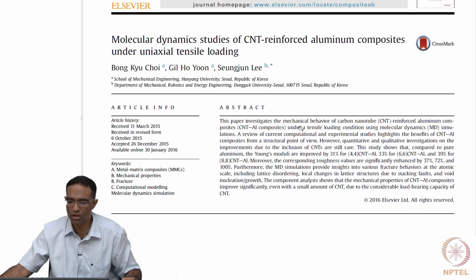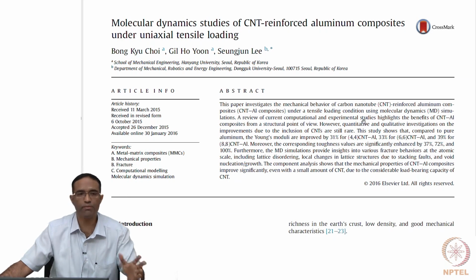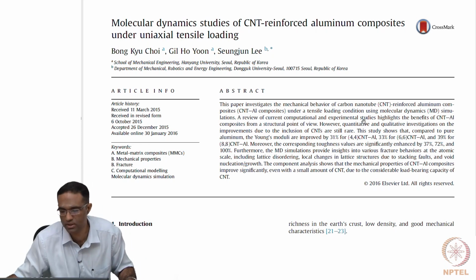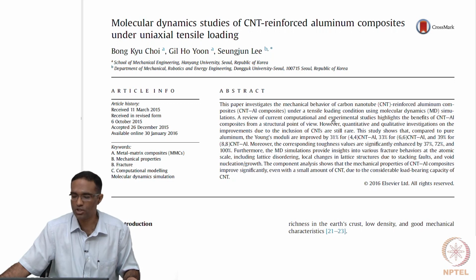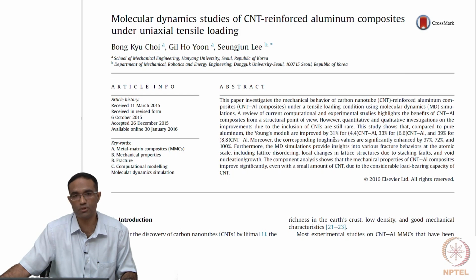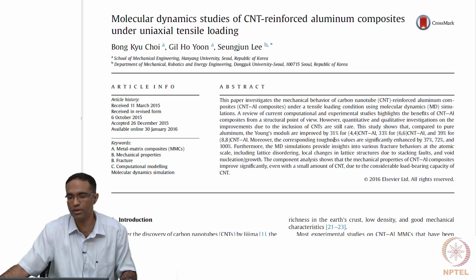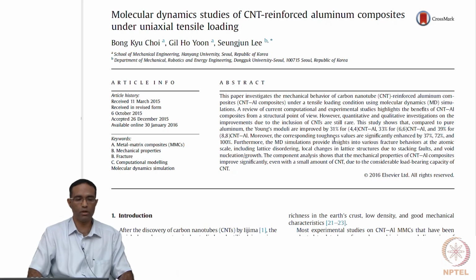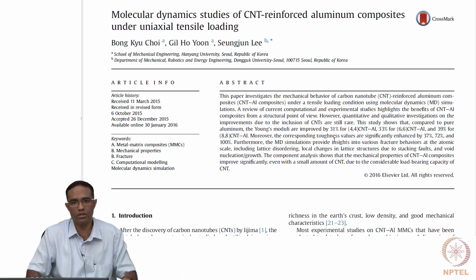If you take a look at the abstract, in brief, what did they find after they performed this analysis? They were able to conclude that the Young's modulus of the composite material improved by nearly 31% for a particular type of carbon nanotube, 33% for another, and nearly 39% for a third, different type of carbon nanotube. They also found that the corresponding toughness values of these composite materials were significantly different when compared to the aluminum itself. In this manner, molecular dynamics simulations can be used to examine the mechanical properties or the qualitative features exhibited by materials when different modifications are done to them.